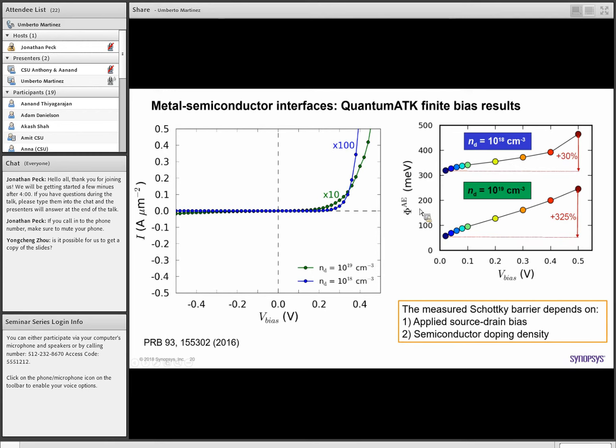So this Schottky barrier, basically, we find that it's not just a simple energy difference between the conduction band of the semiconductor and the Fermi level of the metal.